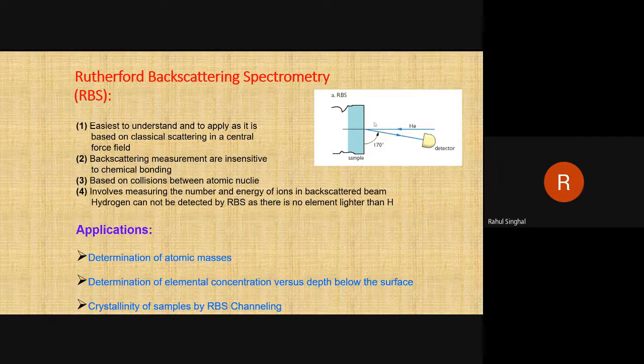Now, in order to perform the backscattering measurement, we should have one accelerator. This is our sample. The beam will hit the atoms of your sample, helium ions will be backscattered, and then we will measure the energy and the yield using solid state detectors. For backscattering, the mass of the incoming ion should always be lesser than the mass of the atoms present in your sample. But suppose you want to measure hydrogen. Hydrogen has a mass lesser than helium. So from RBS, you cannot measure hydrogen. This is a drawback of RBS technique.